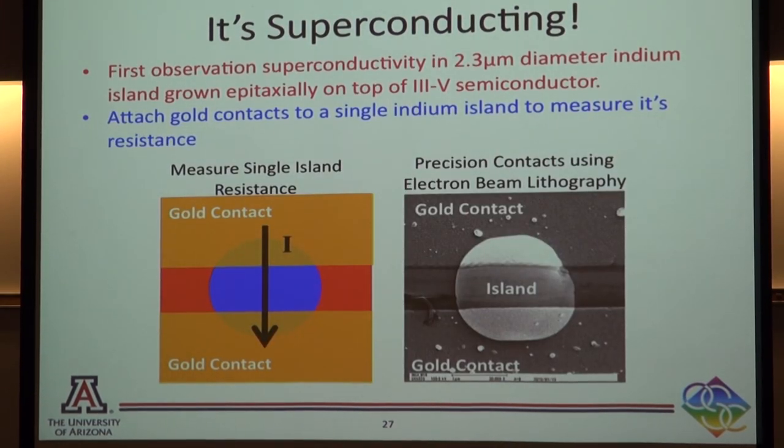So now the obvious next question is, can we make the indium superconducting? The original samples were grown on top of gallium arsenide. Fortunately, it's a very easy test for superconductivity. You put gold electrodes on, and you should see your current drop if you put it in a cryostat. We had a cryostat which goes to 300 millikelvin from the old days of looking at BEC of excitons, so we reinstated it, and my students learned how to run it, fabricate, and put on gold electrodes.